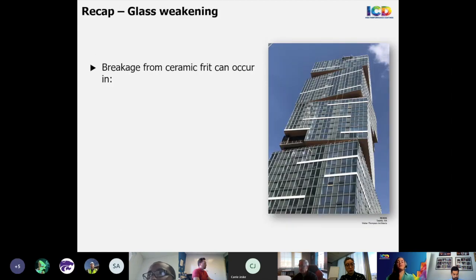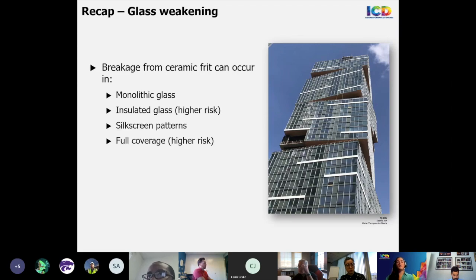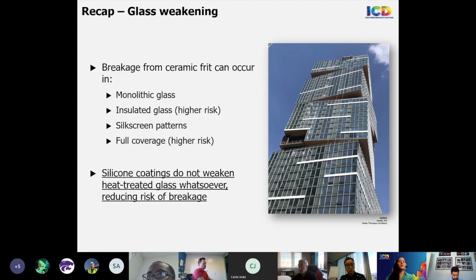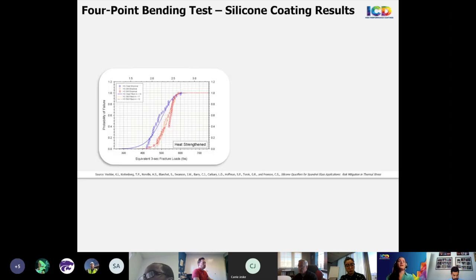So just to quickly go back and recap, overall frit's weakening effects, breakage can occur in monolithic glass, insulated glass at a higher risk, silk screen patterns, and full coverage, which can also have a higher risk. Silicone coatings do not weaken heat-treated glass whatsoever, which can therefore reduce risk in breakage. So I'll show the results of the silicone-coated glass for the 4-point bending test.